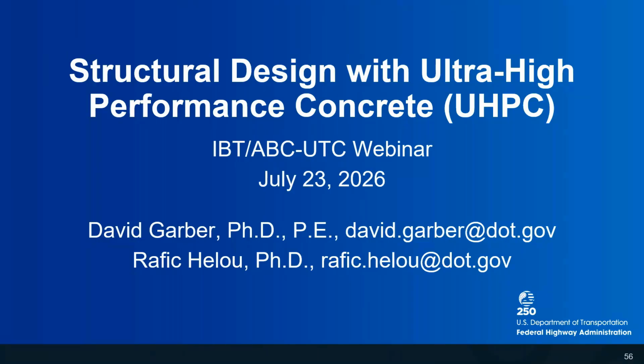Okay. The UHPC code says freshly placed UHPC may have reduced tensile strength from fiber orientation. How do you control this property in the field, and does this cause problems in link slabs? The main way that you control this is your casting procedure and casting method. Generally, you want to place your UHPC at one point and allow it to flow along the length, or you want your UHPC to be cast into already placed UHPC. This will allow your fibers to be aligned in the right direction and give you the tensile properties that you need. There are some states that have done lots of link slabs where you're casting UHPC on one side of the link slab and allowing it to run down the length, and they've seen good performance in those link slabs.